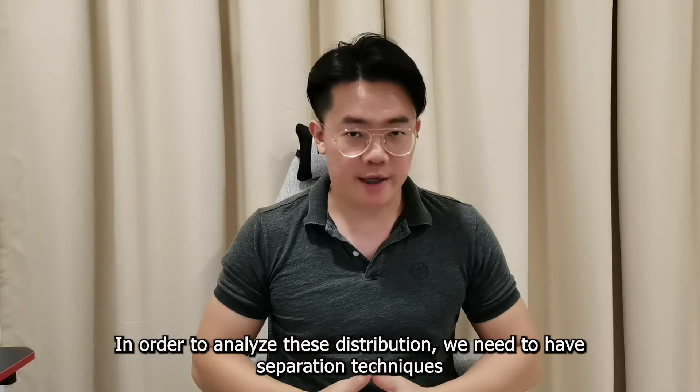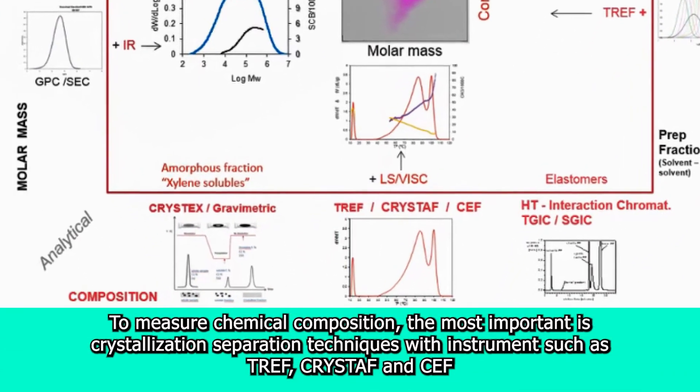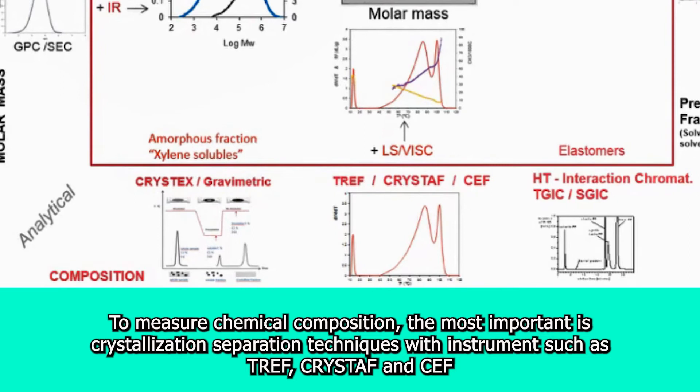In order to analyze this distribution, we need to have separation techniques to measure chemical composition. The most important is the crystallization separation techniques with instruments such as TREF, CRYSTAF, and CEF.